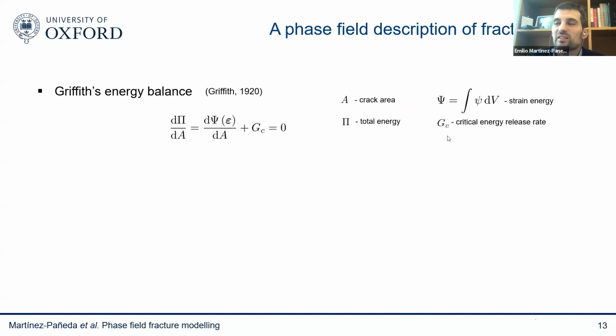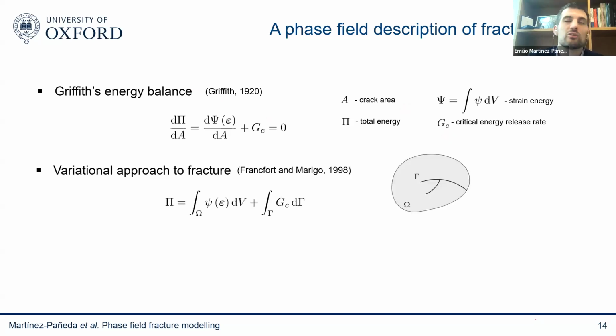And you can express this kind of energy balance, thermodynamic energy balance, in a variational form. And if you do so, and you're able to minimize this functional, then you can naturally predict how cracks evolve as an exchange between stored energy, the energy that is stored in the material, that depends on the mechanical strains, and fracture energy, the energy required to create cracks, basically. But minimizing this functional is complicated, because you don't know where your crack lies. You have this surface gamma, this integral over gamma, and you don't know where your crack lies.